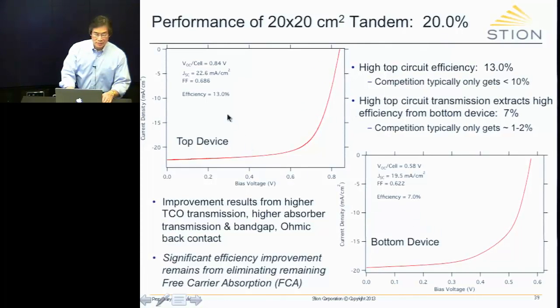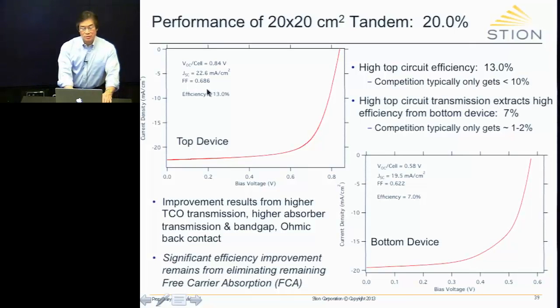The top device is at 13% efficiency with a VOC per cell of 840 millivolts. A quick perspective on that: for silicon, the VOC tends to be on the order of half a volt. The JSC is about 22.6 milliamps per square centimeter. It's high, but it's very close to the limit for a wide band gap of that kind. And the fill factor is about 68, 69%. That's a 20 by 20 device.